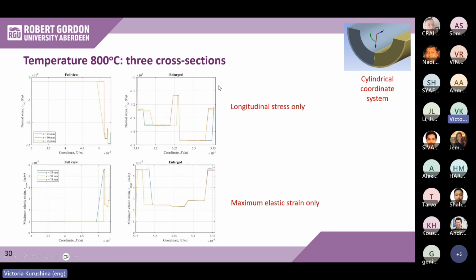If we're looking at the longitudinal stresses only and at the strains, here the borders in between the layers become even more evident. So this is a silver layer, then you've got the cathode layer, especially if you're looking at the longitudinal stress. This is the stress in the electrolyte, after the stress in the anode layer, and finished with the layer of interconnect. So in terms of the radial coordinate coming through all the layers, you can see how the layers behave differently.